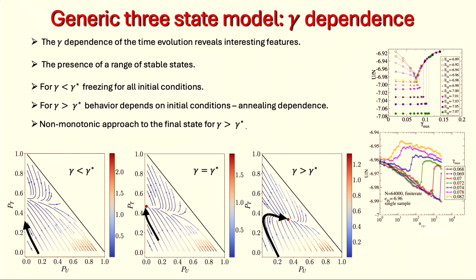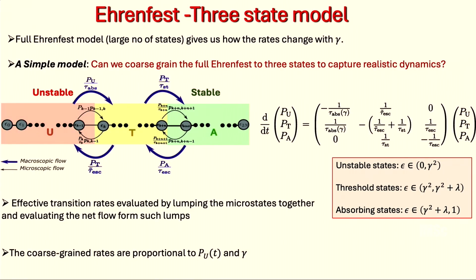is capturing what we see in simulations in a much more complicated setting. And the fact that I have several initial conditions where, even for an amplitude that's greater than the critical amplitude, I can end up with an absorbing state, captures the behavior that we see in simulations of a range of initial conditions for which I don't yield.